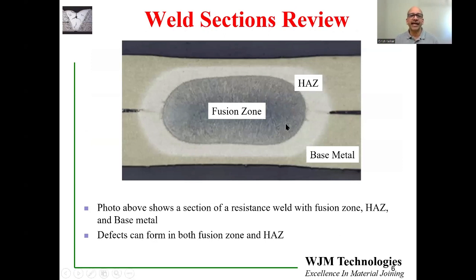Once the sample is etched and photographed, the lab will send you back images, and an image can look something like the photo on the screen. This is a resistance spot weld, and the weld has been made between the two sheets over here, and the cross-section has been taken around the diameter of the spot. And you can see 3 different zones in the photograph. You see the fusion zone, the heat-affected zone, and the base metal.